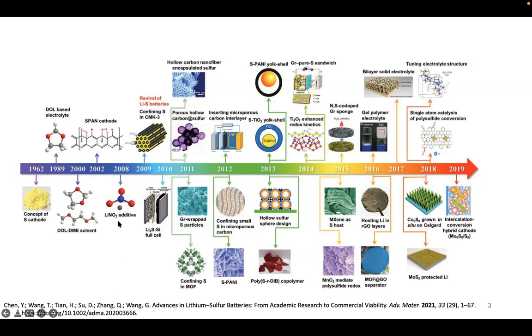Additives like lithium nitrate help to suppress polysulfide shuttling as well. 1 weight percent in your electrolyte will improve the electrochemical cyclability dramatically. And so where are we now? We're now really getting down to not just polysulfide suppression engineering, but atom specific engineering, where we try to add atoms, again, similar to that of hard carbon, to improve the kinetics of the battery, but also improve sulfur redox, because it's extremely sluggish, right?